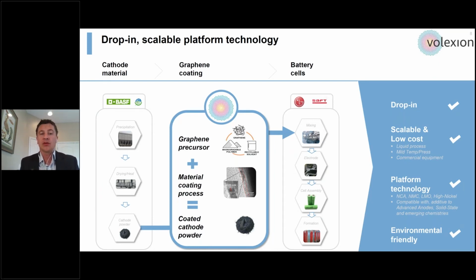In addition to superior performance improvement on the product side, a core feature of our technology is its ability to directly integrate in the existing supply chain and to scale up through a modular deployment of our manufacturing process. So in terms of key feature, our technology is fully drop-in because our technology takes as an input a commercial cathode powder that's made by chemical companies such as BASF or Umicore, for example. And what comes out of our proprietary coating process is a coated cathode powder with our graphene precursor that's exactly of the same form factor as what comes in and can be used directly as an input to the mixing step of battery manufacturing without having to retrofit or change in any way, shape, or form the manufacturing process. So that makes our technology fully drop-in.